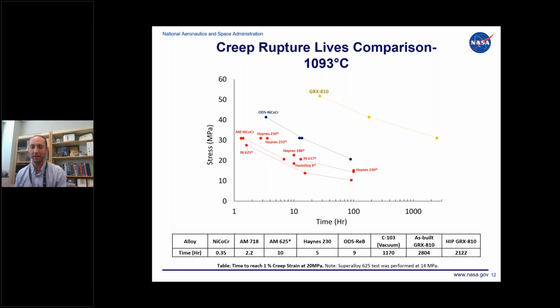The HIP version was 2,100 hours, and those numbers are actually better than C103 in a high vacuum, which was 1,170 hours. Our hope is that GRX-810 can replace 718 and 625 that are being used in really high temperature applications, but maybe even replace C103 that's being used in some lower temperature applications, just because of how costly C103 is.